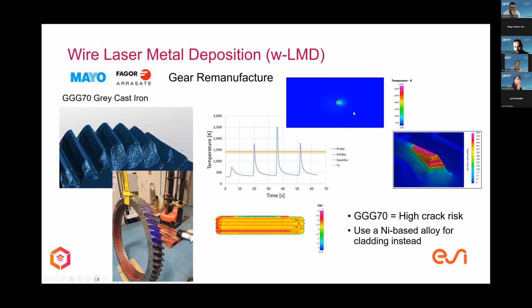So we looked at deposition strategies provided by Marco, and we look at the thermal history of these repairs. So you see when the laser is far away from the actual repair line, we see a preliminary preheating. Then the laser is closer, so we have some melting, and then the laser moves on that point, and then it moves away. Based on this thermal history, we can look at the material behavior and judge whether it's going to crack or not. The crack susceptibility was predicted to be very high for this material. So instead of using a similar steel, a nickel-based alloy was used instead. There will be more details on that later on.